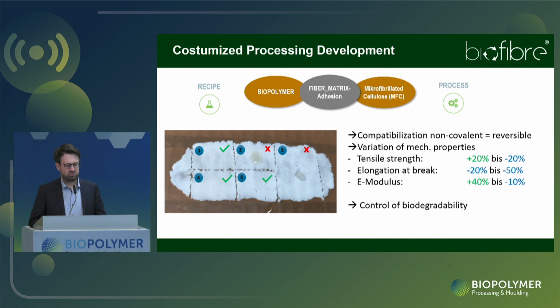So we tested quite a lot of different compatibilizers. Some worked quite well, some didn't work very good. So it was just an easy drop test, and it was our first approach to this. But testing it in a compounding unit revealed that just by exchanging the compatibilizer, you can drastically change the material properties. For example, you can have the tensile strength in a ratio between 20% plus to 20% minus. Or most strikingly was the E modulus, where you can enhance the E modulus because of the embedment of the fibers into the matrix, which was much more elaborated when you use the compatibilizer.